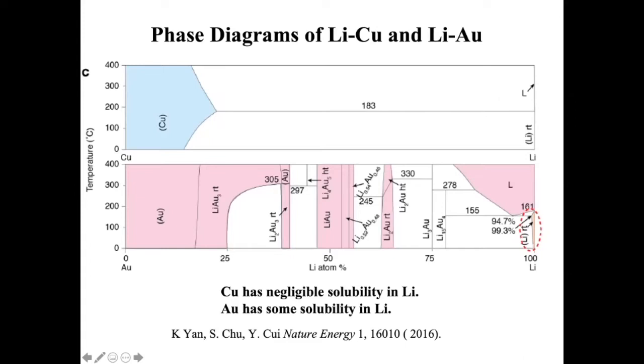So we come to an explanation. Look at the phase diagram between copper and lithium on the top, gold and lithium at the bottom right here. And you look at the most right-hand side, lithium and copper. The copper has negligible solubility in lithium. But gold would have some solubility. You look at this domain.